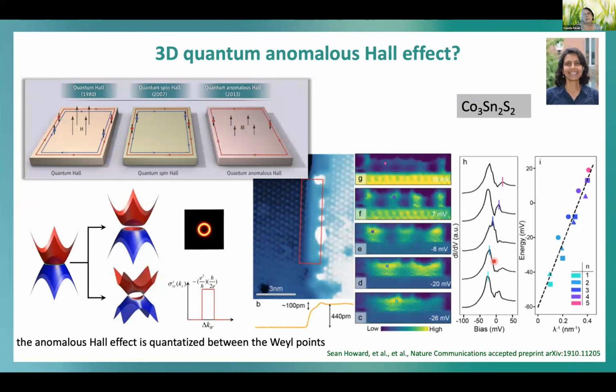We then looked at the edges of this material because we recognized that the anomalous Hall conductivity per layer is nearly close to the quantized value we expect, and this motivated us to look with STM at the edges of this material.